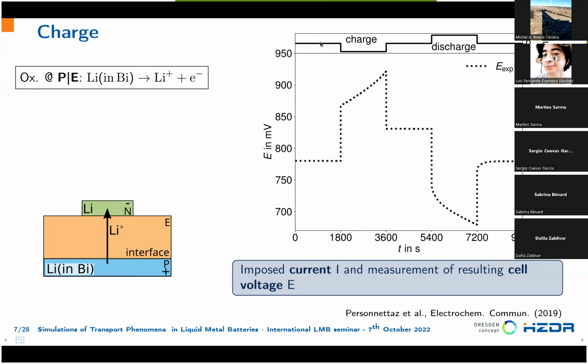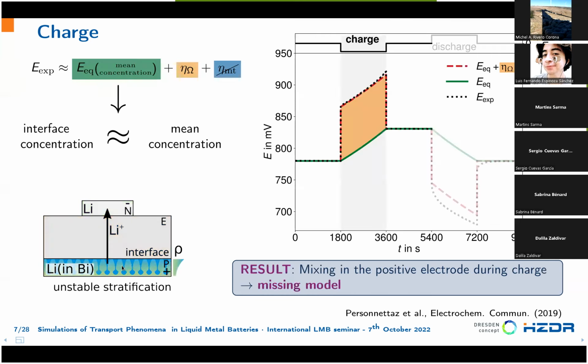So we see here, current is at the beginning 0. Then we have a charge phase. Then again, the current is set to 0, a discharge phase, and again a quiet phase with no current. And here the dotted line is the recorded voltage. During charge, we have this oxidation at the interface. This means we remove lithium from the lithium bismuth alloy in the positive electrode.